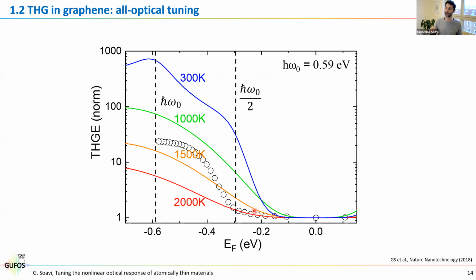And the reason is that the type of experiments that we're doing here is using ultra short pulses. So we are shining light with something like 100 femtosecond pulse duration. And in this shorter time frame, the electronic temperature is different from the lattice temperature. So the lattice is still at 300 Kelvin, but in this 100 femtoseconds, while we generate third harmonic, the electronic temperature is much higher because the energy that we transfer to the material doesn't have enough time to scatter to the lattice via electron-phonon scattering. So within the third harmonic generation, our electronic temperature can easily reach thousands of Kelvin.